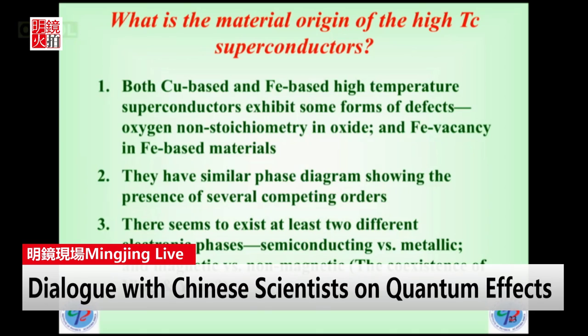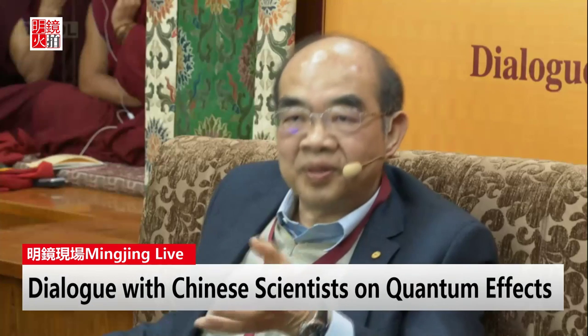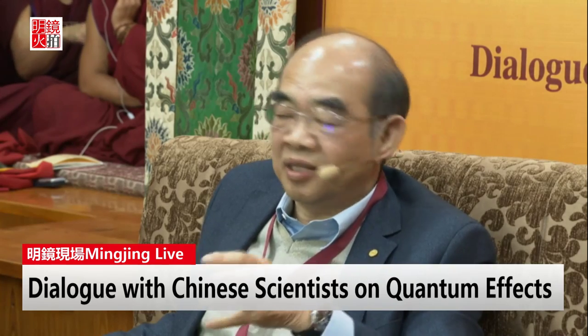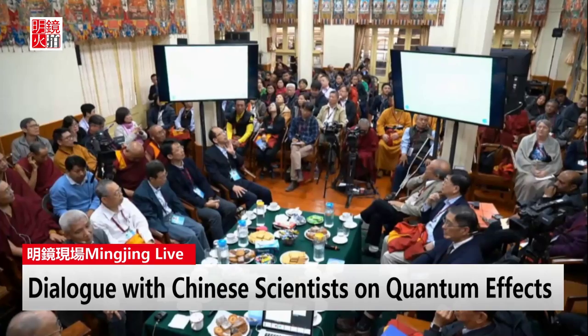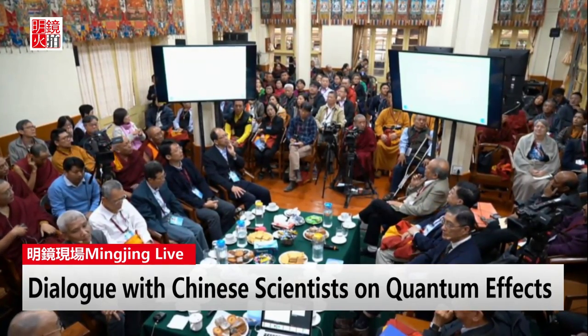So the key here, from our understanding today, especially from our own research, on the material origin of this high Tc, I can conclude this. Both copper-based and iron-based high-temperature superconductors have some form of defect, either oxygen non-stoichiometry in the oxide, or iron vacancy in the iron-based material. And they both display similar phase diagrams, showing several very interesting states next to each other. There seem to exist at least two different electronic states that are necessary when you are properly doping: semiconducting versus metallic, and magnetic and non-magnetic. And we Chinese always talk about this yin and yang, the coexistence.